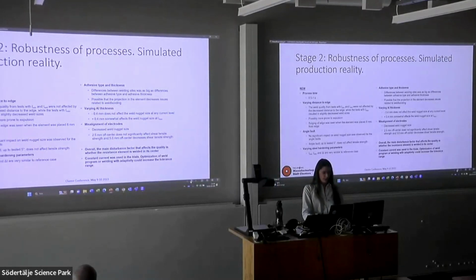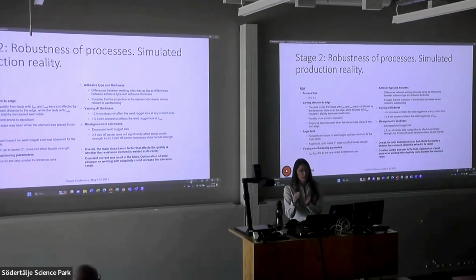So to summarize, general process time, 0.5 to 1 second for resistance element welding. I forgot to mention this, but of course, when we do actually place the elements closer to the edge of the material, you do see deformation and you see bulging. We also tested varying steel hardening parameters, so not optimal hardening condition. This did not impact the process at all.